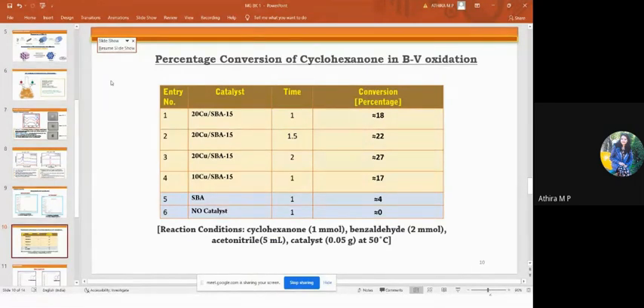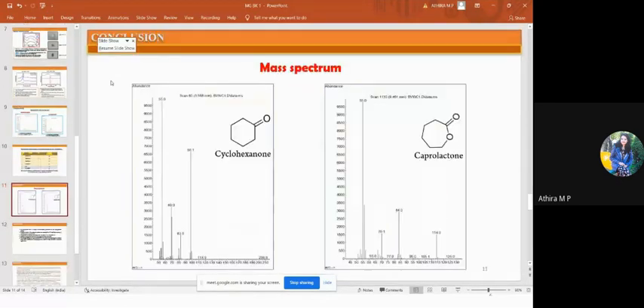The table shows that similar conversions were obtained for the 10 weight percent and 20 weight percent copper catalysts, around 17 and 18% respectively. The progress of the reaction was monitored using 20 copper SBA, and after 2 hours conversion was around 27%. There is negligible conversion when the reaction was done with SBA-15. In short, copper SBA-15 can act as a promising catalyst for cyclohexanone conversion to caprolactone. And this is the mass spectrum of cyclohexanone and caprolactone from GCMS.